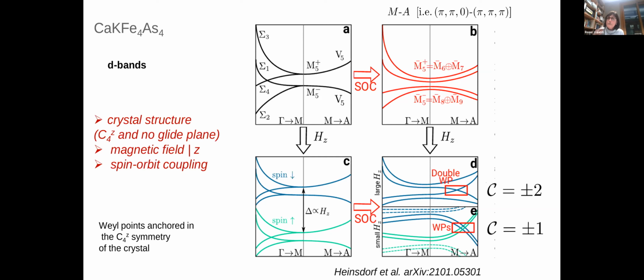So now what we want to do is basically, for this fourfold nodal line, break all the possible degeneracies to get at the end of the day just non-degenerate bands where a possible crossing can happen. So one way of breaking this degeneracy is by applying a magnetic field along Z. So we are going to break the Kramers degeneracy, and we will just get twofold nodal lines. Another way of breaking this degeneracy is by including the effects of spin-orbit coupling in this system, which will also break this degeneracy into twofold bands.